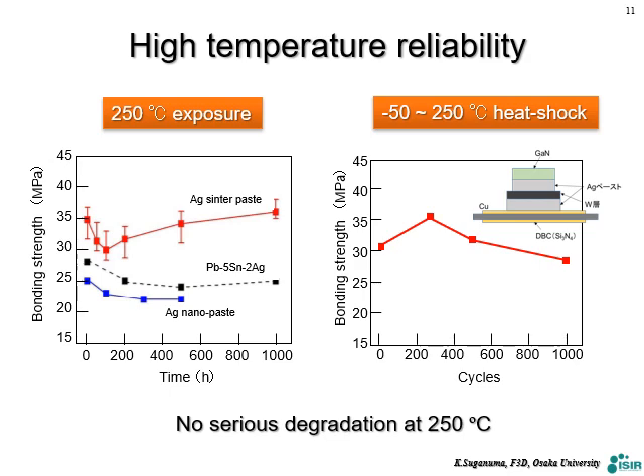I'm showing the high temperature stability of a silver sinter joint assembly. In this case, gallium nitride is bonded onto DBC, with high temperature exposure at 250 degrees C, very high temperature, up to 1000 hours. There is no degradation from the initial; some changes, but after 1000 hours it maintains the initial strength like this. So it is a great advantage compared to other materials. And for heat shock from minus 50 to 250 degrees C, a very severe heat shock test, the initial strength can be maintained even after 1000 cycles. There is no serious degradation by using silver sinter joining.